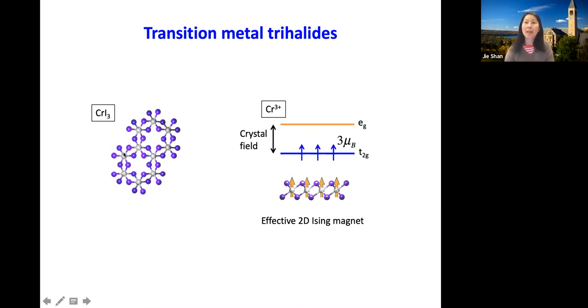The magnetic atom has 6 electrons, and it donates 3 to the iodine atoms, so we have 3 left. The crystal field splits the levels into T2g and Eg levels, and the 3 electrons sit in the T2g and all align. The material has very strong spin-orbit coupling, which is in the out-of-plane direction, so the spins are aligned either up or down. Effectively, you can think of this as close to a 2-dimensional Ising magnet.